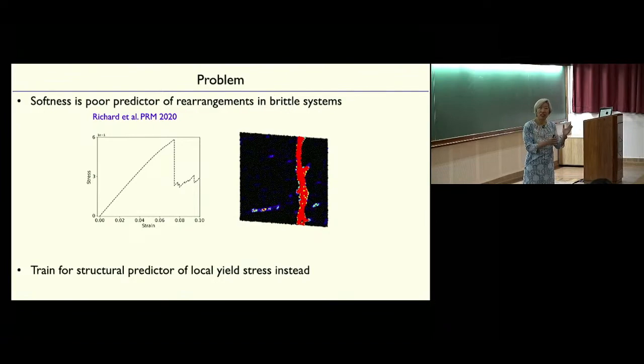So all this thing about tuning ductility, or tuning the degree of strain localization, it's all empirical. Oh, if I quench it to a lower temperature, it's more brittle. Oh, if I shorten the interaction range relative to the particle size, it becomes more brittle. But why? And that's what we're setting out to answer. So what are you changing when you're doing that that makes a difference?